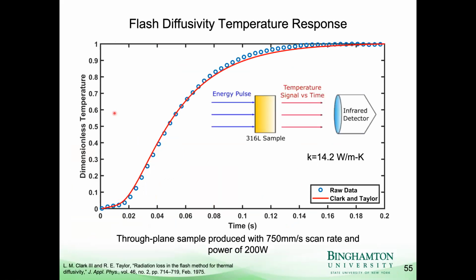So next we took all these samples and we measured the thermal properties with flash diffusivity. In flash diffusivity, we take our sample and we send a very brief pulse of radiation to the top surface. And then we measure the temperature response on the other side of the sample. And based on the time it takes for that thermal wave to penetrate the sample, we can determine the thermal diffusivity and thermal conductivity of the material.